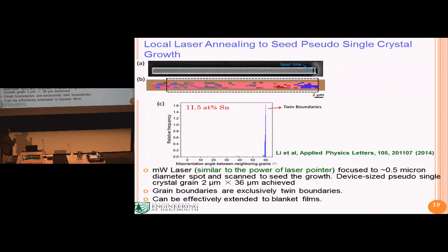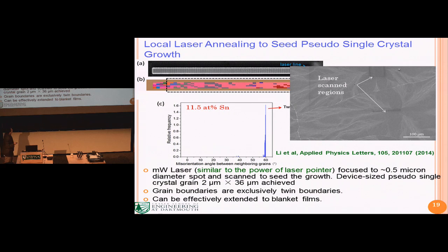You can see originally there were competing grains which are twins to one another. One of them accidentally wins and essentially extends across the crystal. So this is a piece of almost single crystal there. All the boundaries you have, we confirm, are twin boundaries. We also proved that the same concept can be used to improve the quality of blanket films. So just for fun, Haofeng has written two laser patterns, this square and this rectangle. You can see after the crystallization, these two serve as nucleation centers. So the crystal is growing out from here.